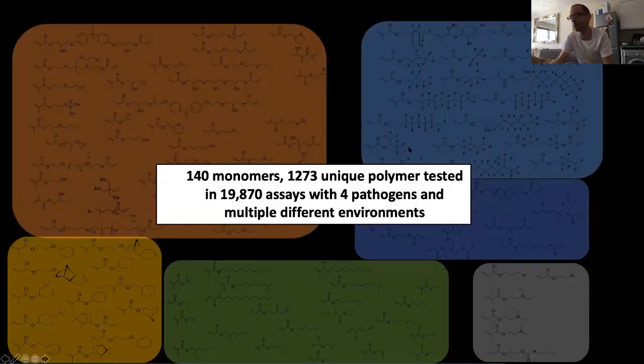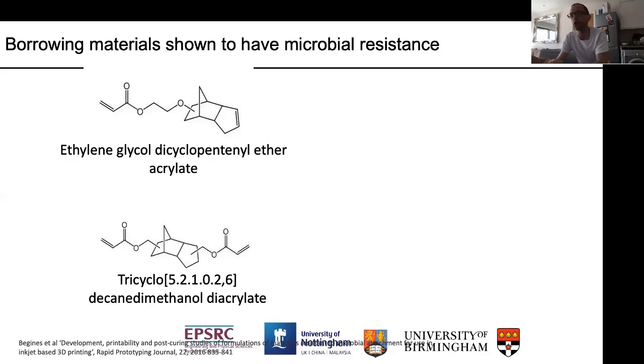These are the sort of examples of the kind of monomers that we were faced with. Our colleagues screened those, identified them in a high throughput manner, which of those had the cell-instructive properties, and then simply by looking at the kinds of viscosities that these monomers had, we were able to make a reasonable guess about which of those monomers would be printable in an inkjet printer. So we down-selected two monomers. They're essentially a monofunctional or difunctional pairing of monomers that were shown to be resistant to bacterial attachment.